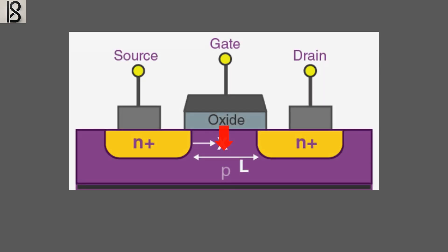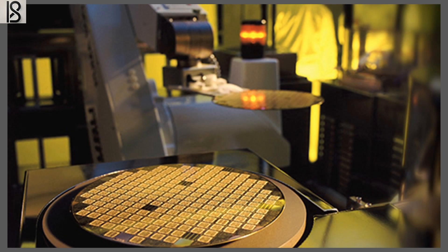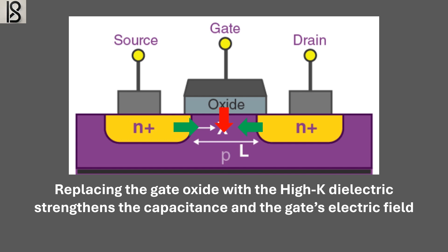Short channel effects arise from the interference of electric fields coming from the source and drain. The original planar gate is positioned above the channel, making contact with only one side. The electric field extends downward through the channel into the silicon, controlling the channel's behavior. However, the source and drain also produce their own electric fields, which spread horizontally into the channel, interfering with gate control. For decades, the industry anticipated this issue and managed to lessen the impact by lowering the voltage, heavily doping the channel, or reducing the depth of the source or drain. Another key change was to replace the gate oxide — originally made of silicon oxide — with one that has a higher dielectric constant, boosting the gate's capacitance and making the electric field projected by the gate stronger, allowing it to have more control over the channel.